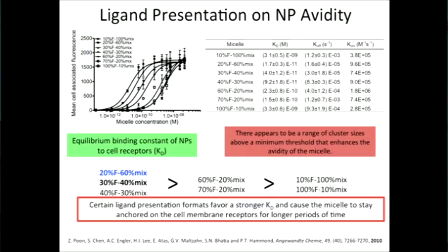Now, they have the same amount of folate molecule on them. And we sort of did this by mixing them with non-functionalized material so that everything has roughly 2,000 folates per micelle. And yet, this is binding more strongly. And as we begin to increase the cluster size, we see the number stays around 10 to the minus 11 for a while and then begins to jump up. So we're seeing a slow decline in the ability for it to bind as it gets larger. So there's some sort of sweet spot here.